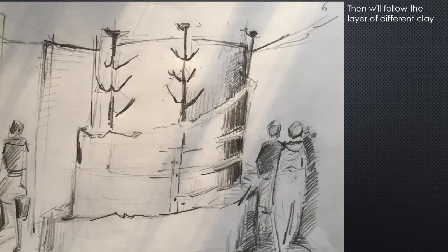vertically aligned iron bands. While the huge molds in the pits were slowly drying, the workers erected walls of mud bricks to the north and the south of the molds, and thus created an evenly wide heating room around the mold. For the success of the work, even more so with the new technique with the iron bands, the heat had to be equal on all sides of the mold. At least in one pit, there was an opening in the wall to the north to regulate the air supply in the heating room. When all this work was done, the formers made way for the casters.